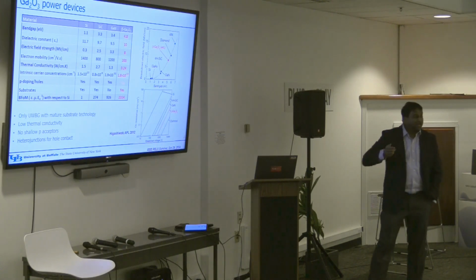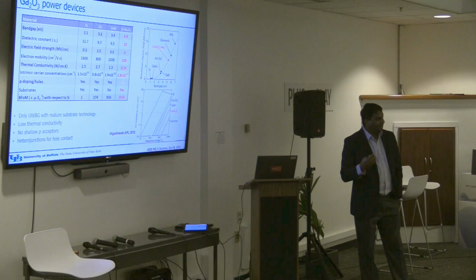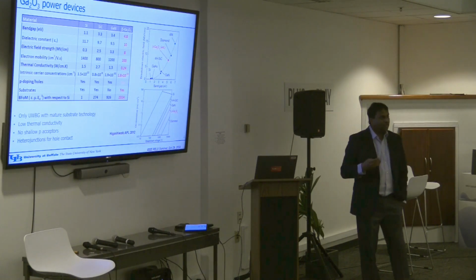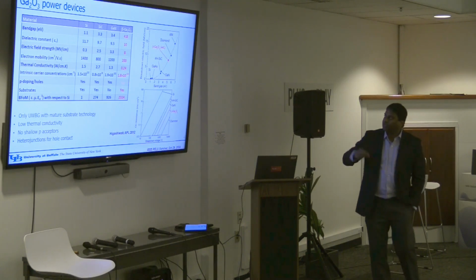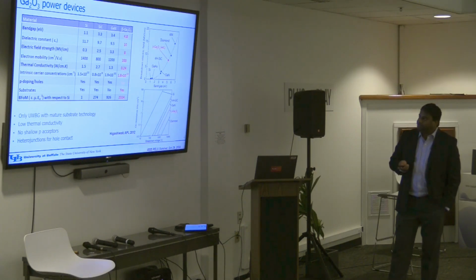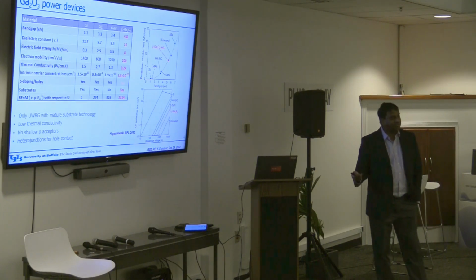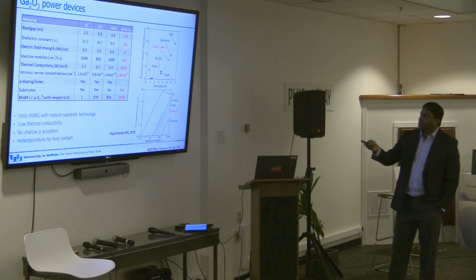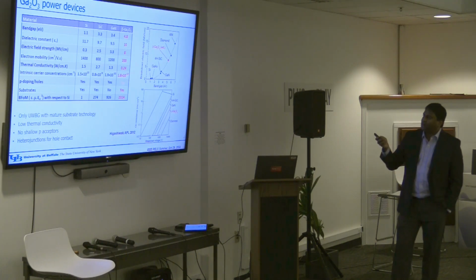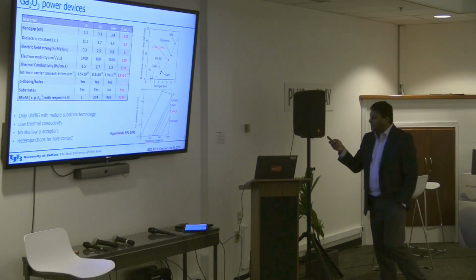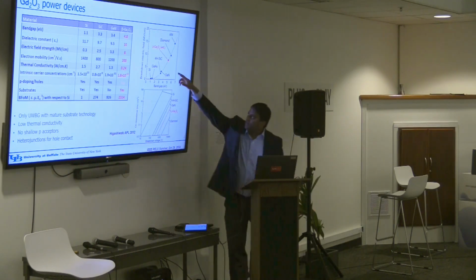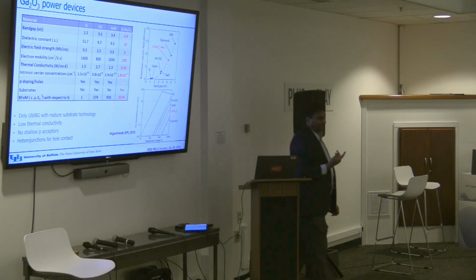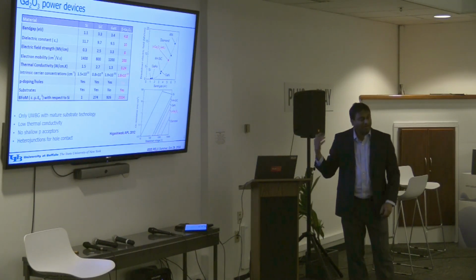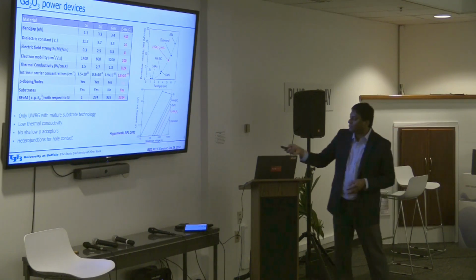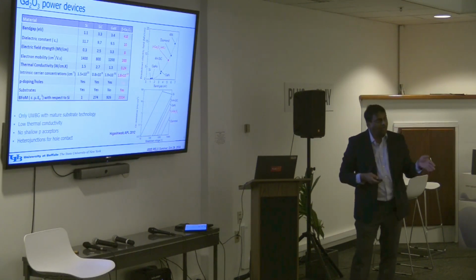So gallium oxide is an ultra wide bandgap semiconductor. I think the community here right now knows about gallium nitride and silicon carbide, which we know are wide bandgap semiconductors, with a bandgap around 3.3 to 3.4 eV. And we know the advantages of using wide bandgap semiconductors over silicon: higher power, higher voltages, higher power densities. With the same argument, gallium oxide has a bandgap of 4.8 eV, which results in a critical electric field strength of 8 megavolts per centimeter, and as a result you can get low on-resistances and high voltages. This is the whole argument about moving from silicon to wide bandgap semiconductors.